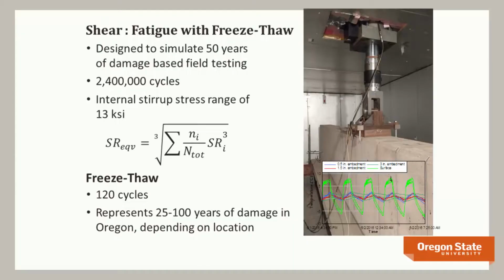Based on field measurements of real bridges, the stress ranges that we're producing are amplified so that we can accelerate the service life, and we're using Miner's rule essentially to come up with an equivalent stress range. And for producing 13 KSI stress range in the stirrups, we can do about 2.4 million cycles, and we can make the argument that represents about 50 years of service life.